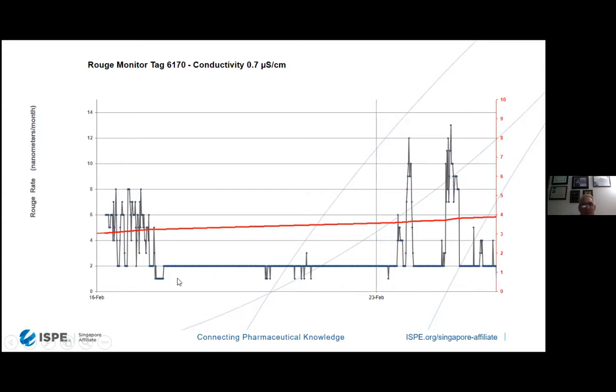Well, it's very simple. What happens is we open up the valves to the points of use to fill up the vessels. And when you fill up the vessels, the contact time, the residence time of the water against the piping is lessened, because I'm producing the WFI water, it's sitting in storage, and it's going out to the point of use. It's not recirculating in the same piping 24/7. So as we're doing filling operations and usages, the rouge rate is very small. When we turn off the point of use, the rouge rate goes up once again.